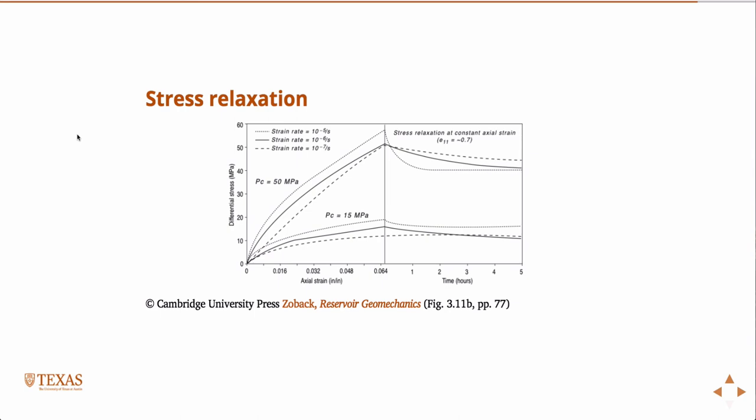There's not only a pressure dependence, but there's a rate dependence. I haven't even talked about the stress relaxation, which is the point of this plot. Over, up until this point, the material is strained to like 6.5% strain, and then it's held fixed. This is time beyond that. You see that the stress decays, relaxes, as time goes on.